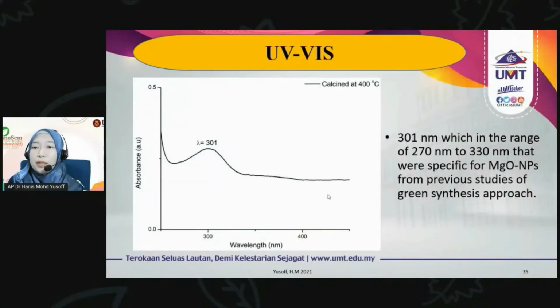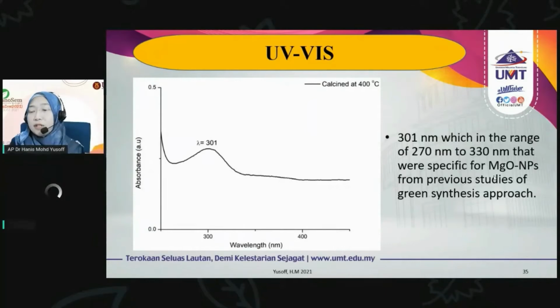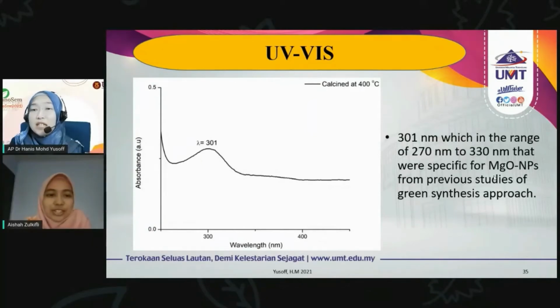Okay, so we also look at the UV-Vis properties, and we only managed to do it at the 400 degrees Celsius calcination temperature. And the wavelength obtained is at 301 nanometers, which falls within the range specific for magnesium oxide nanoparticles from previous studies. So the range is from 270 to 330.